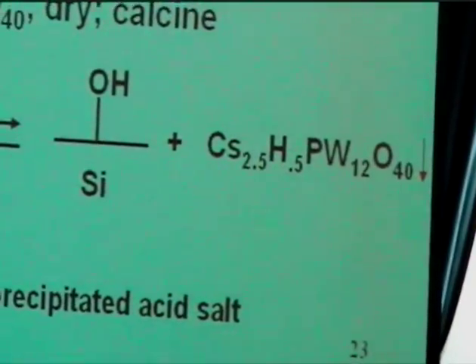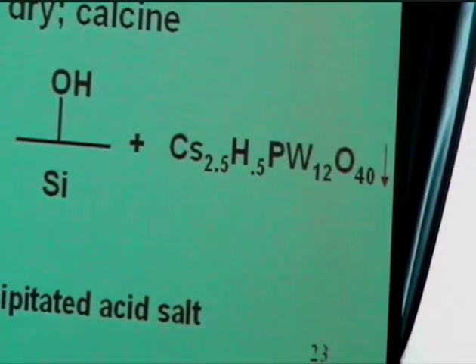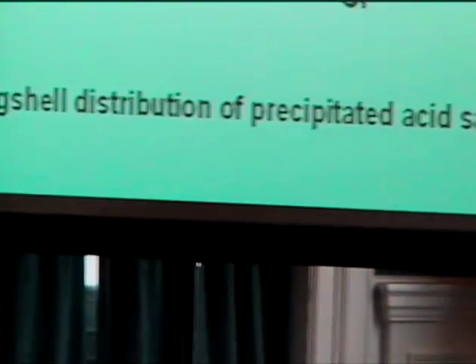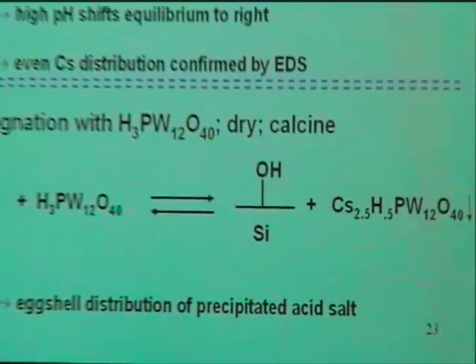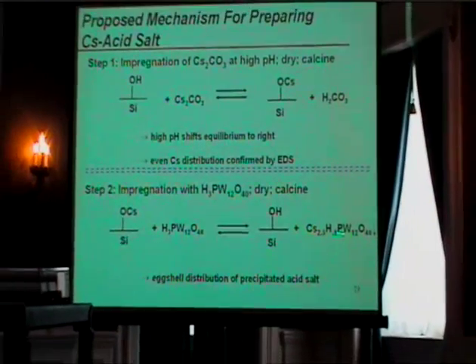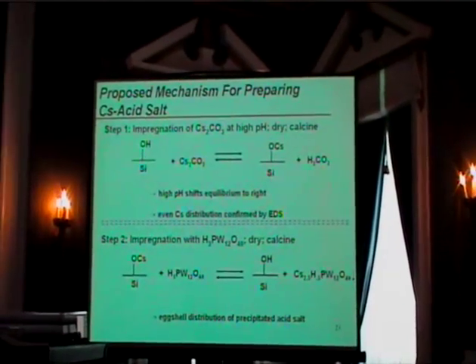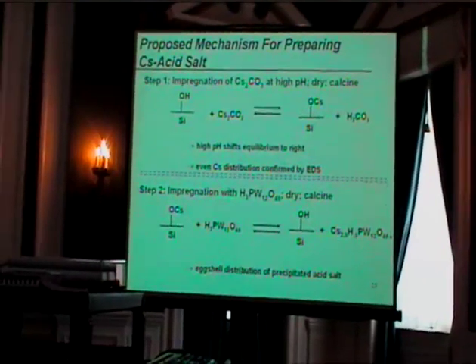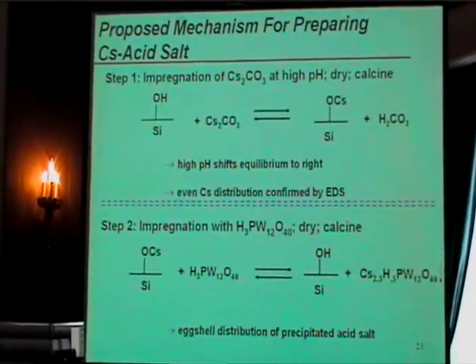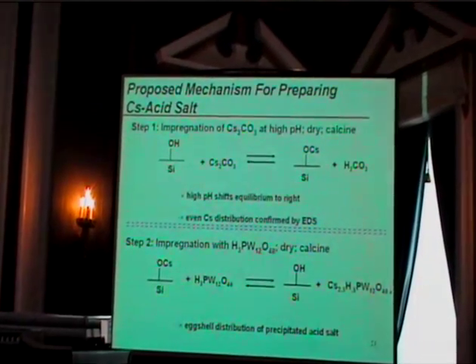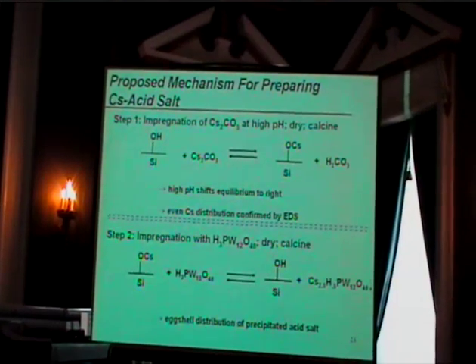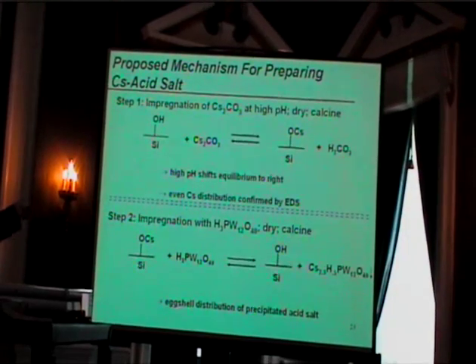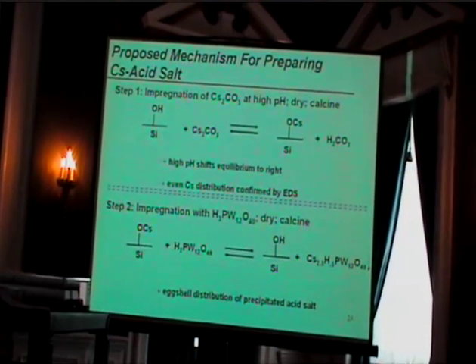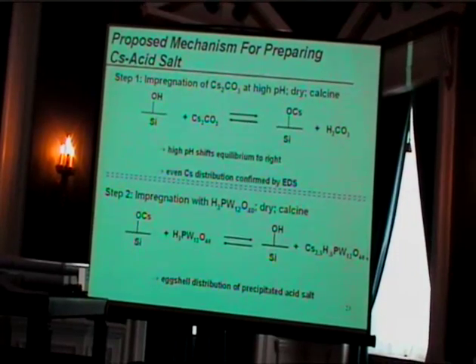So this becomes H3 minus X, cesium X. As you go further in, X increases, you get more and more cesium rich until you reach a critical concentration where that now becomes insoluble. And it's like a chromatographic deposition that occurs as you reach that critical point and make something of about that stoichiometry that forms here. And that's how we got to this, actually it should be eggshell distribution of precipitated acid salt. So you have a very complicated structure and a very interesting way of putting it into a pellet, but it's actually very simple. All it is is two impregnations. So it's a way of trying to control very complicated things in a very simple way.